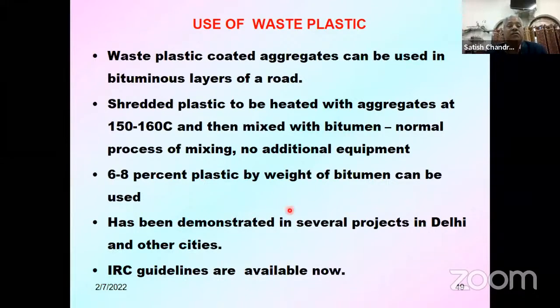Now, dry process is more successful than wet process, because in wet process, there is always a problem of miscibility, or you can say compatibility. And in dry process, this shredded plastic is heated with aggregate at 150 to 160 degrees centigrade, and then mixed with bitumen. Normal process of mixing, no additional equipment are required, and we can use 6 to 8% plastic by weight of bitumen. It has been demonstrated in several projects in Delhi, in Himachal Pradesh, Arunachal Pradesh, in Haryana also, and it is successful.